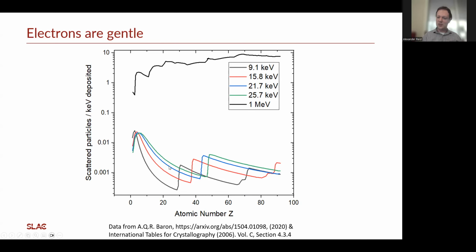And you see in this relative comparison between various energies of X-ray, going from about the 9 keV that's typically used at LCLS-I, up to the energies now accessible at LCLS and other XFELs, that over the full range, we still have between a few tens of times to about 1,000 times advantage in the number of quanta of scattering information that we can get for a unit of deposited energy. And so this matters when going down to very thin and very small samples, where the probe can start to pump the structure, and where you may not want that much energy deposited into the system.